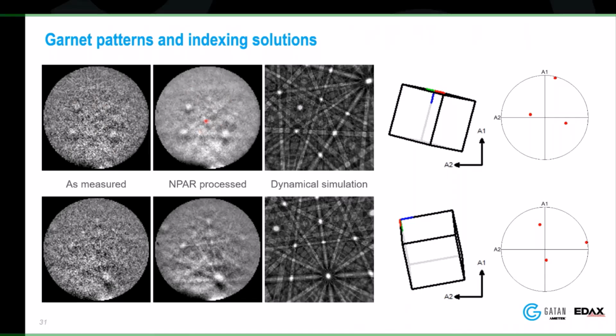And then if I compare this and get an orientation off of this, we run this through spherical indexing and get an orientation off of it. This right here is the orientation solution that we get, and the orientation here is from the dynamical simulation. This, I think, is where you really start to understand the advantages of spherical indexing with geological materials. If you start looking at things like garnet, down here in this pattern, we can see there's a good zone axis right here. We can see that in all 3 of these.